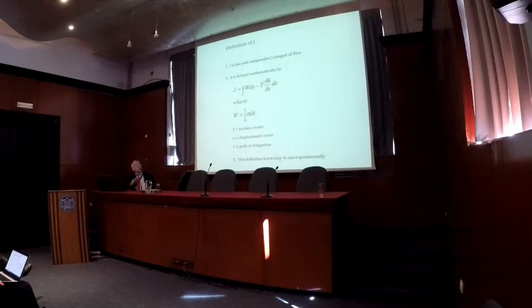J is defined by Jim Rice as an integral. It's a path-independent integral. Gamma is the path. W is a strain energy density. And T is a traction vector, and U is a displacement vector. So this whole thing is the real definition of the J. This definition can be useful for numerical work, stress analysis and the like. In a laboratory, though, it's not very useful. It's hard to calculate a term like that in the laboratory.